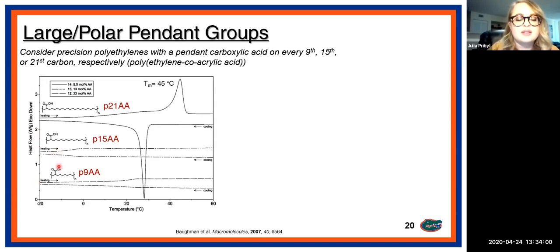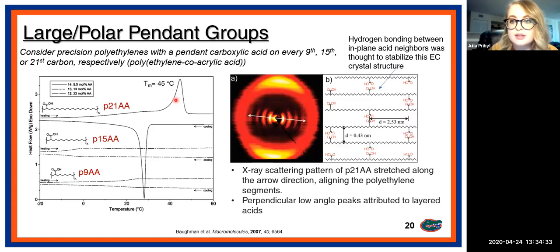So as I noted before, sometimes when you put these functional groups close together, they disrupt the crystal structure so much that they can't actually crystallize. So when the carboxylic acid is on every 15th or every 9th carbon, we actually see no melting endotherm. So these two materials are completely amorphous. But when we put the carboxylic acid on every 21st carbon, we see a nice melting endotherm at about 45 degrees Celsius. So in this work, this was the target to look at, okay, now what kind of semicrystalline secondary structure do we find? And this is what we found. So I'm going to walk you through this.